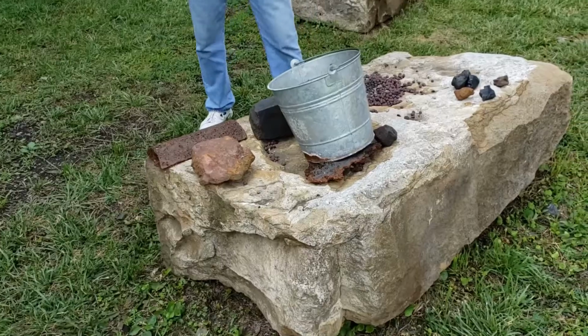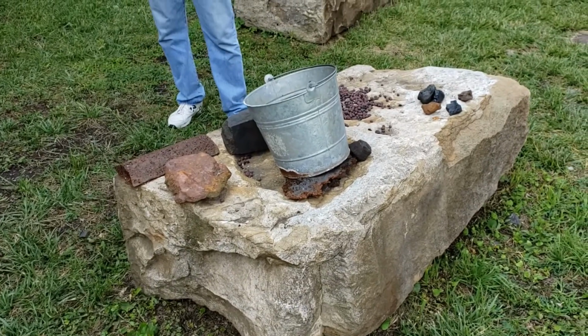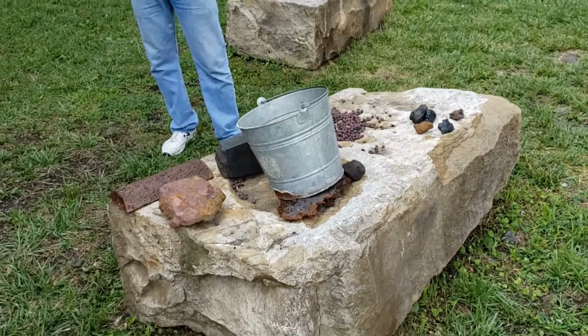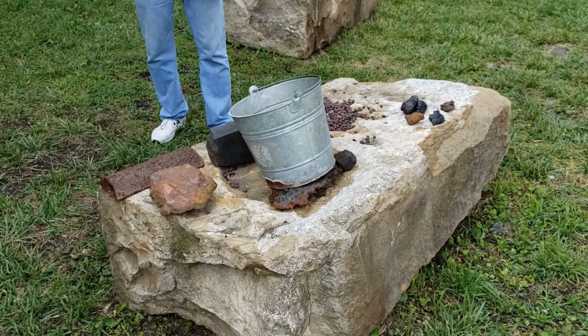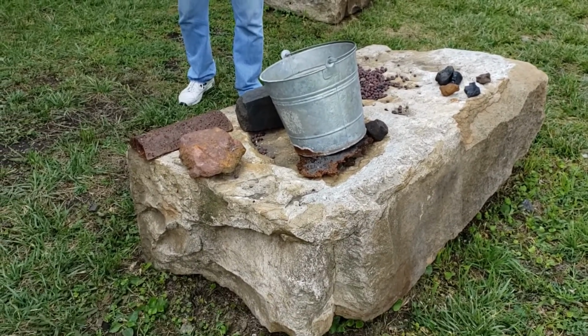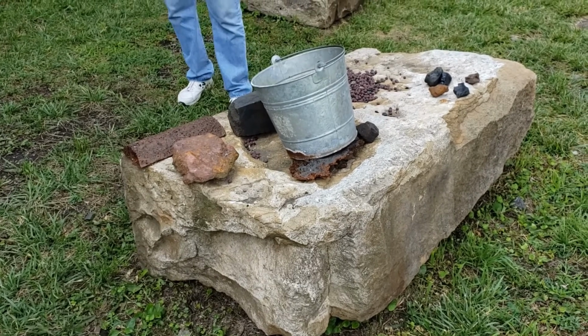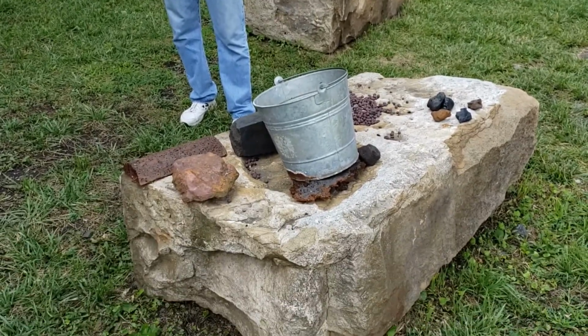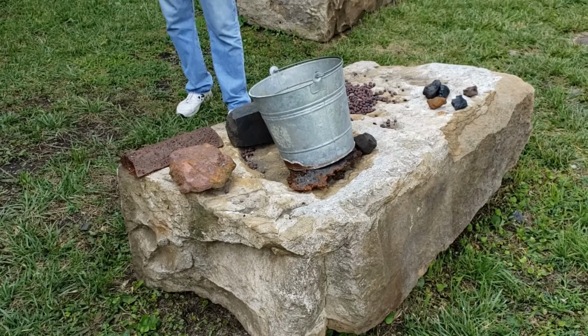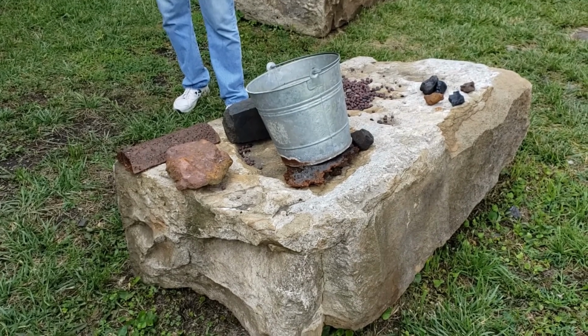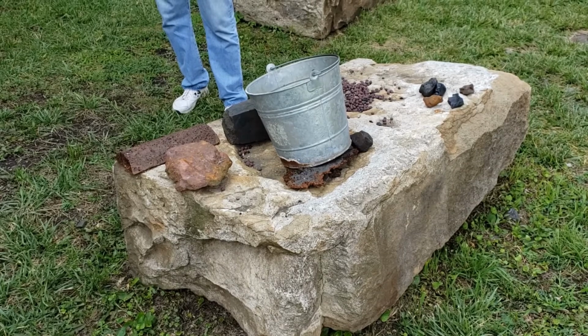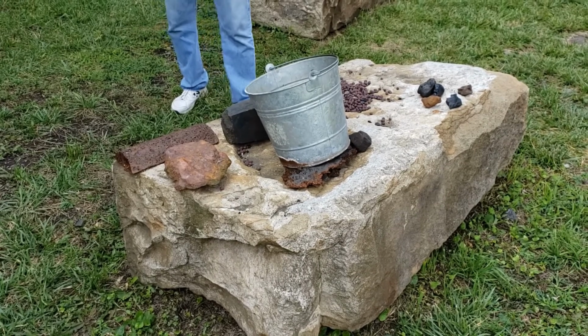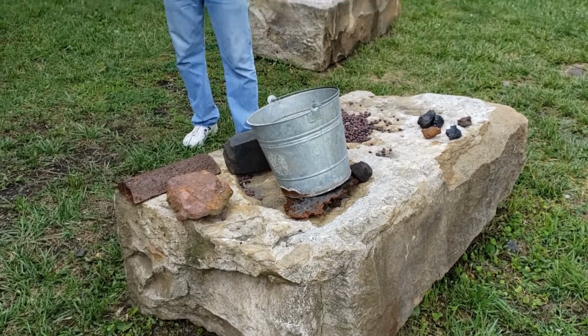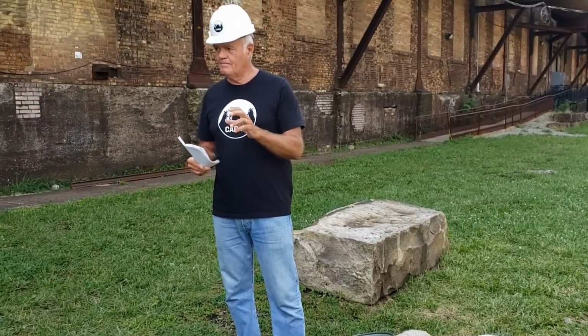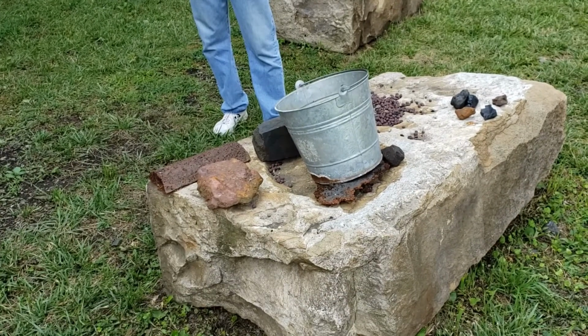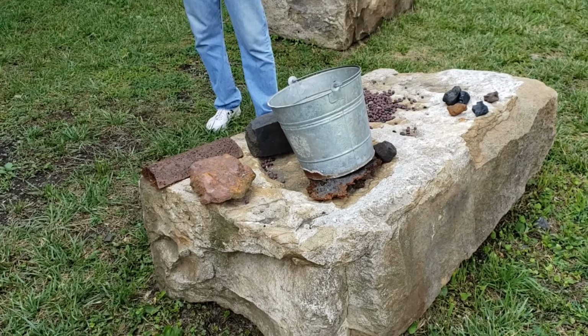So you get a lot of iron ore, and that has a lot of iron in it. It has about 60% iron in that material there, and that's why you get it out, and you want to get the iron out of that. They also took, the fuel was not coal. It was coal at the beginning, but then they found a way to get the volatiles out of the coal and make coke out of it. So if you had coal, you'd have about 60% carbon in it, but once you take all the volatiles out, you can get it up to 87% carbon.